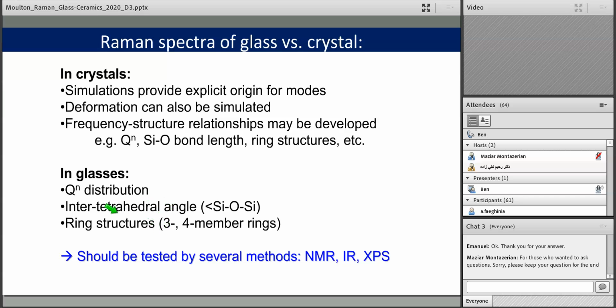We've noted that the low frequency region is related to bending and rocking, so it may be related to this intertetrahedral angle, but it shouldn't be taken as an absolute guarantee, and that this relationship of the QN units is transferable between the glasses and crystals. But always there's this question mark overlying things because we don't have the theory. So you should test this by using another independent probe, such as infrared or X-ray photoelectron spectroscopy.